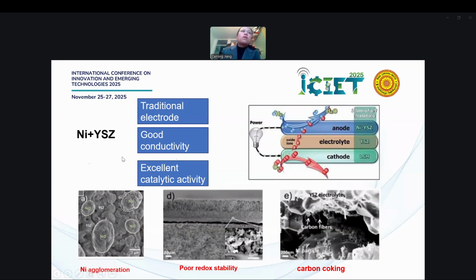Yeah, and according to the requirement, nickel YSZ is a traditional anode, so it has good conductivity, up to 1,000 Siemens per centimeter, and has excellent catalytic activity towards fuels like methane, hydrogen, hydrocarbon, and even carbon monoxide. And carbon monoxide is a disaster in proton conducting electrolyte fuel cells. But here, it's not a problem at all.